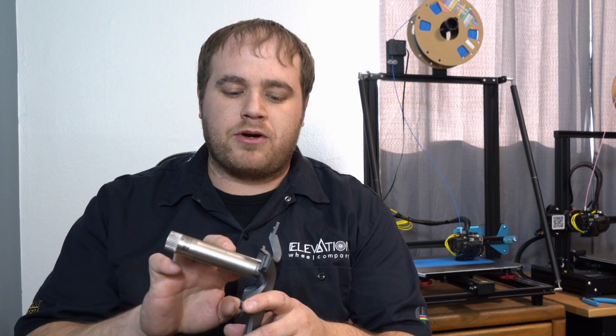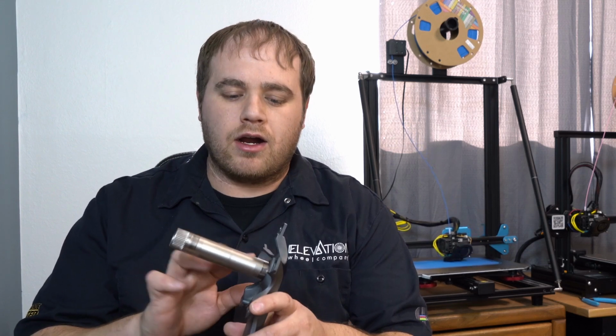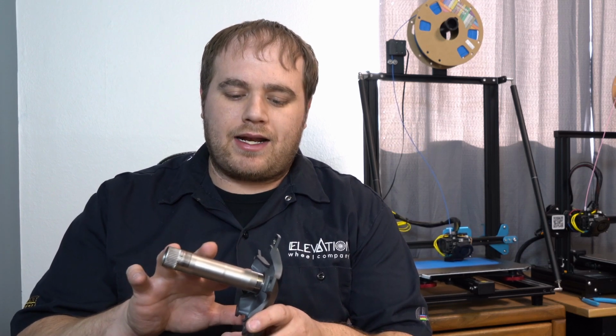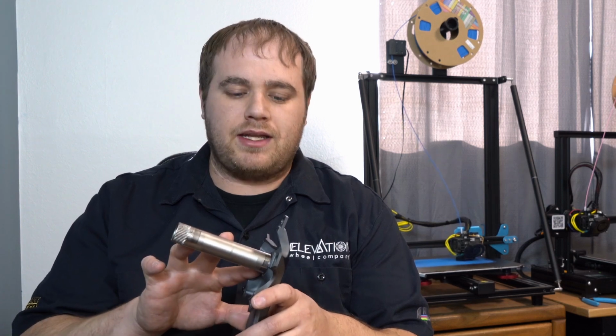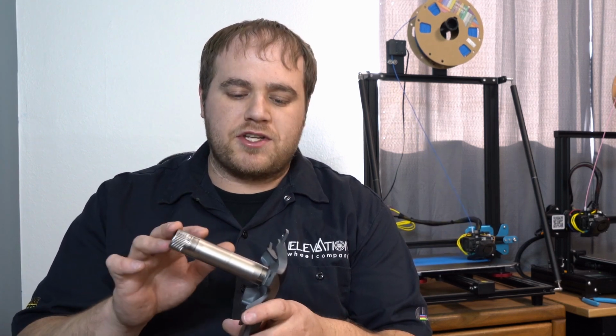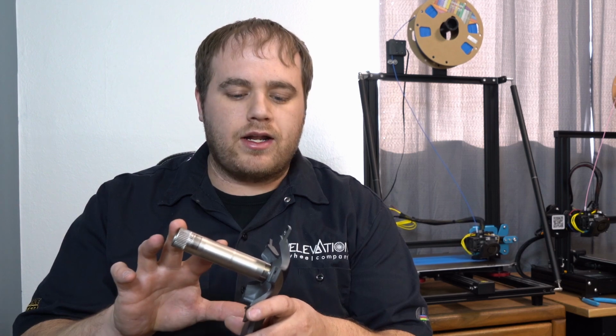So re-anodizing parts isn't anything new, and this isn't going to be a tutorial on how you anodize parts. The difficulty is with Shimano cranks specifically, they have this steel spindle that is permanently bonded to the aluminum crank arm. In anodizing, you cannot have the steel in with the aluminum because it will completely eat away at it, leaving both the spindle and the crank arm itself destroyed.